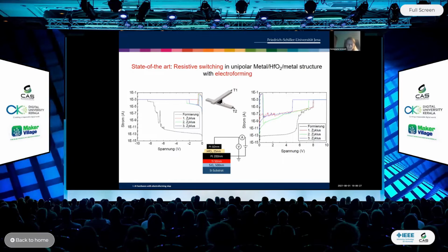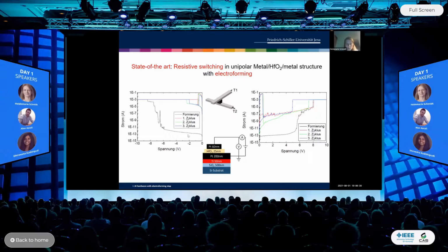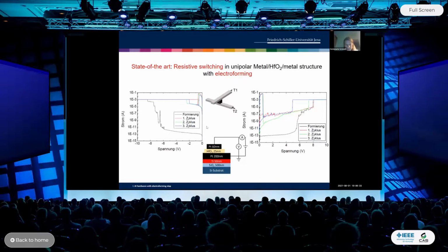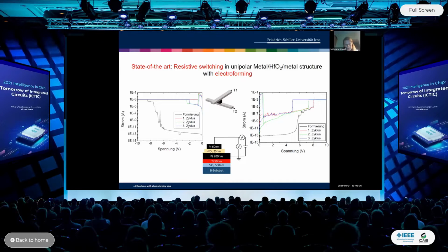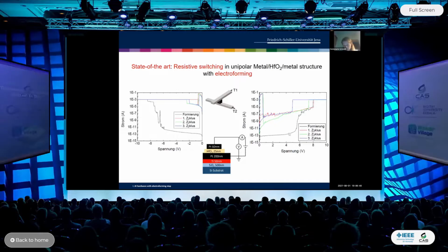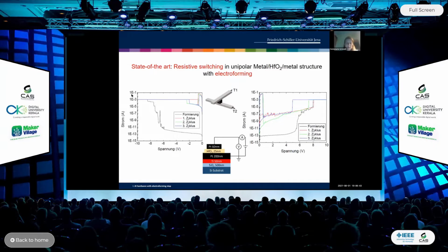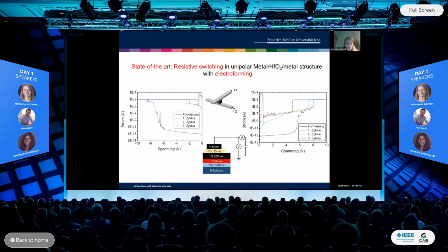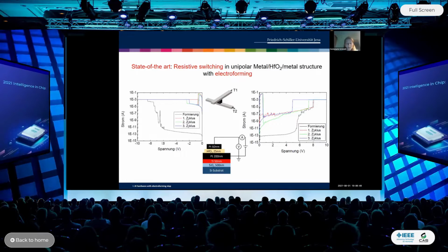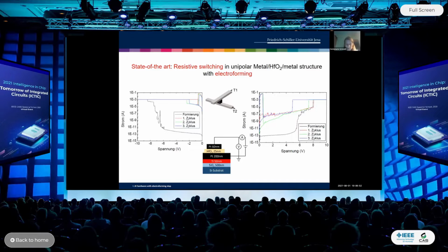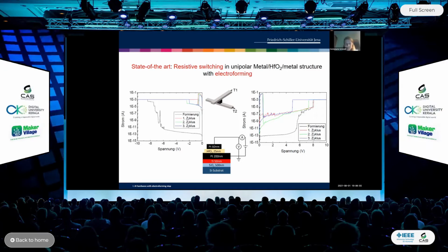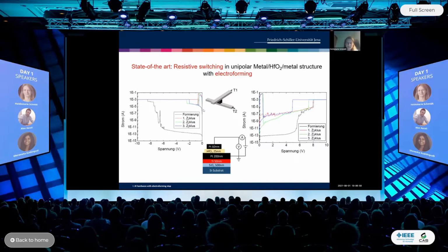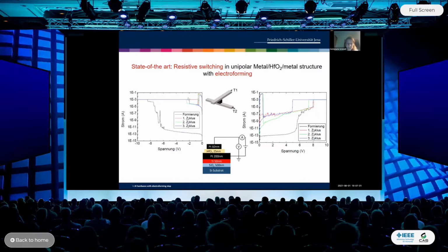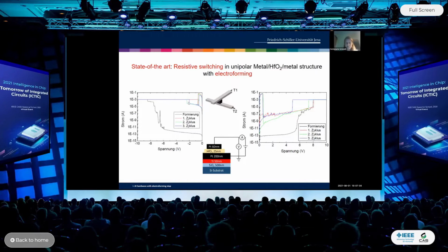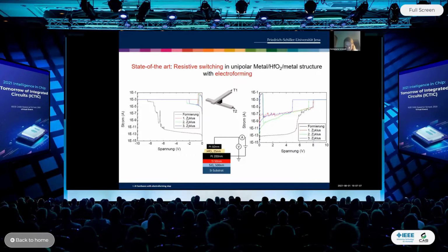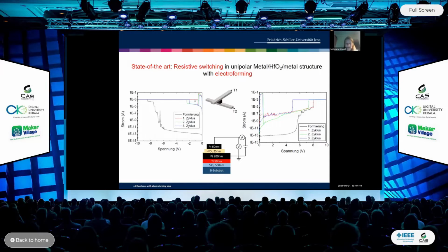Normally, let's say the state-of-the-art memristors work as follows. If you apply a bias for the first time between the two electrodes, for example, this is the black line if it's a negative bias, or this is also here the black line if it's a positive bias, you ramp it, and then the corresponding current only increases above a certain compliance level if this forming bias is very large. And if you ramp the bias a second and third time and further on, then you do not need such a large bias to change the resistance state of this memristor between the high resistance state with a small current and the low resistance state with a high current.